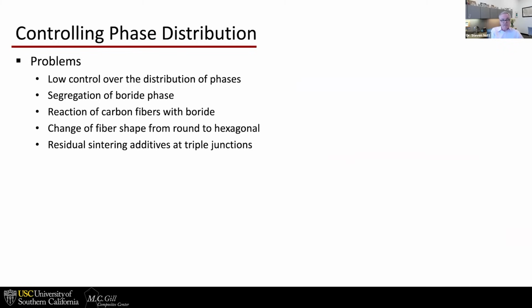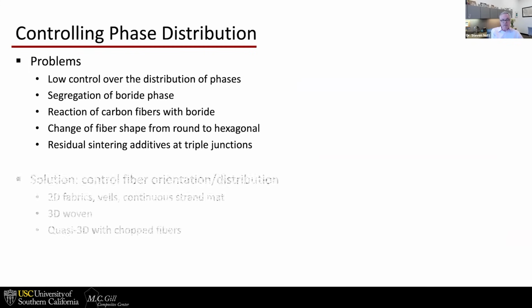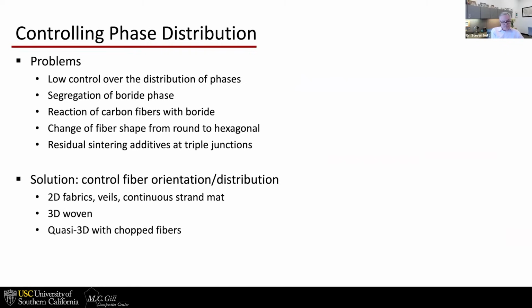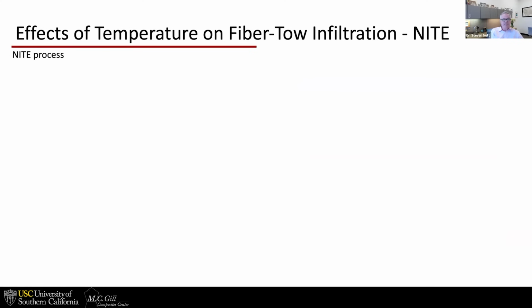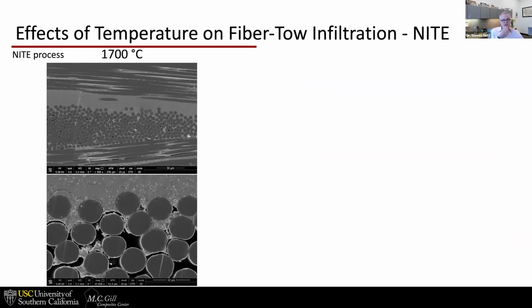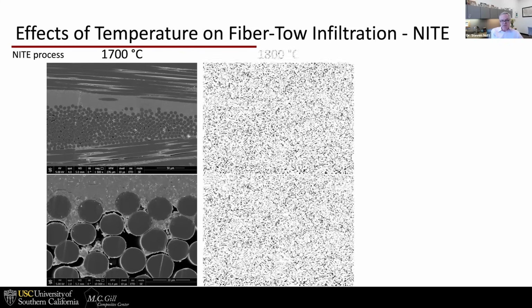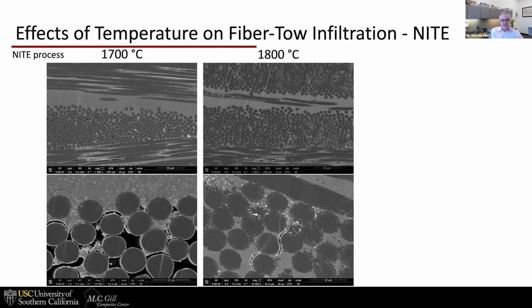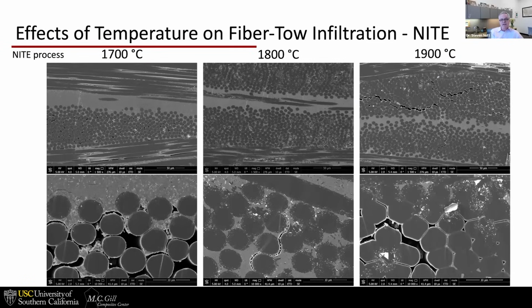Yeah, controlling phase distribution is really important. That's something that vendors have to deal with. There are a lot of different ways to go with this, and different fiber forms to play with. And finally, we're going to talk about this nanopowder infiltration and transient eutectic approach, which has basically been licensed by Axiom, and they're using it. But we're looking at the effects of sintering temperature on the infiltration and distribution of phases in the structures to try and guide the selection of process parameters.